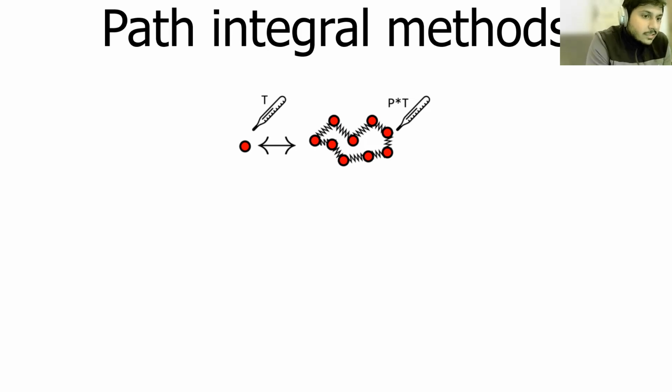And then what else? There are some more approximations. I guess you're approximating your nuclei moving classically rather than quantumly. Yes, so that is one of the major approximations in ab initio MD, that after you get your forces, you drive your dynamics in a Newtonian manner, or you treat atoms as billiard balls. Now, electrons are quantum, but let me give you this harsh reality. Some nuclei can also behave quantum mechanically, especially protons. And we'll see a few examples where they actually do.